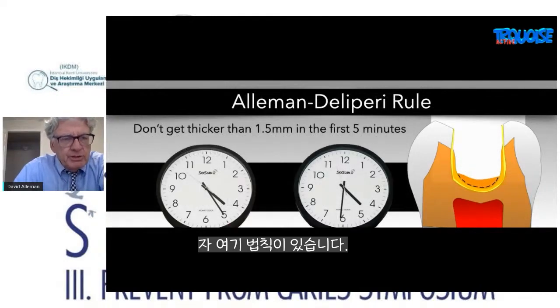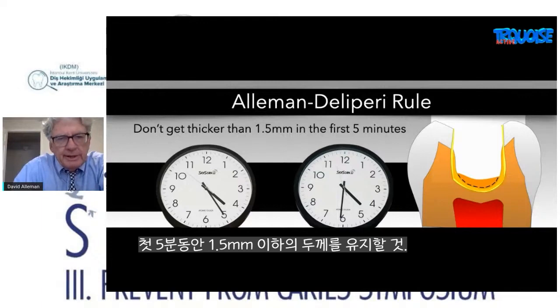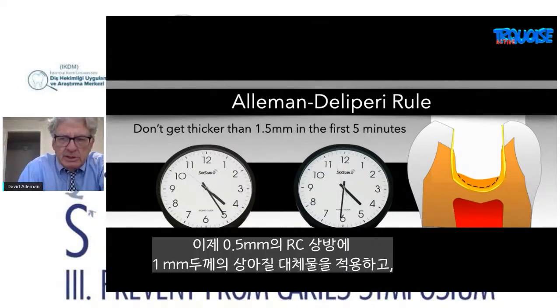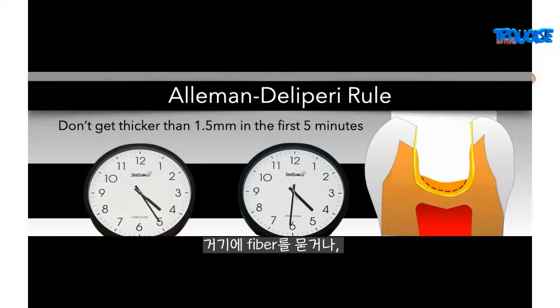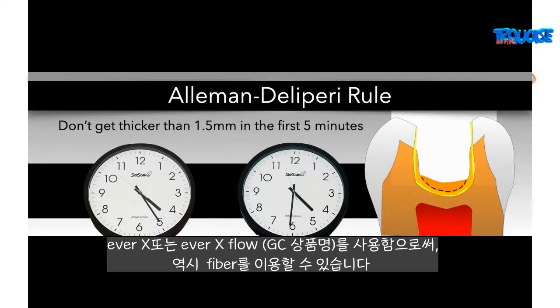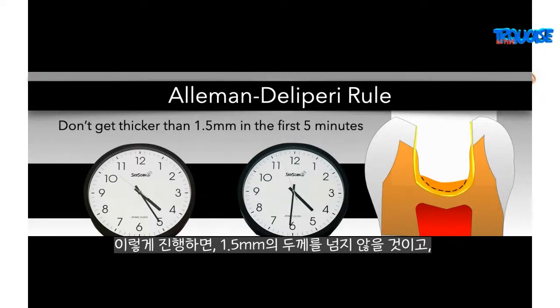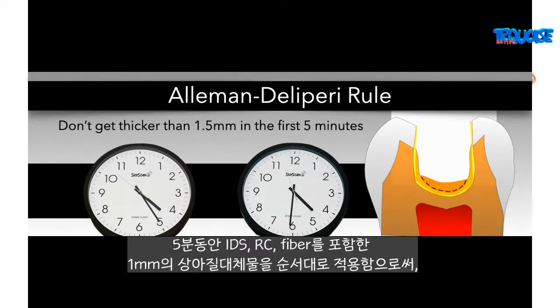So this is the rule. Don't get thicker than 1.5 millimeters in the first 5 minutes. Now, you can also put 1 millimeter on top of your 0.5 millimeter resin coating. That resin coating and now that 1 millimeter of dentin replacement here. If you embed fiber into this, like everX or everX Flow, and you put that at that time, you will not exceed that 1.5 millimeters in 5 minutes.